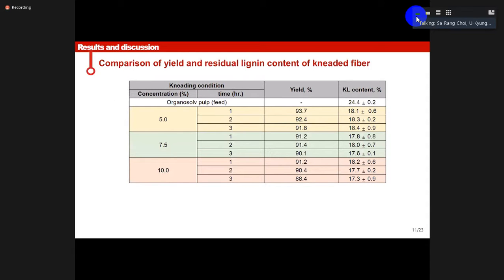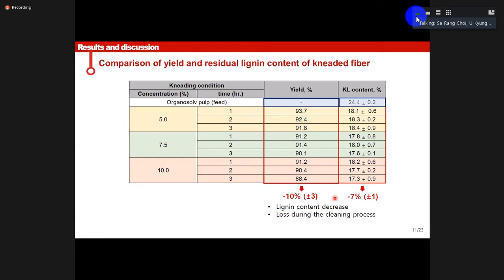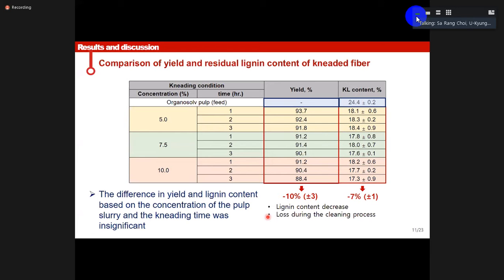The results and discussion. These slides show the yield and lignin content of kneaded pulp according to the pulp concentration and kneading time. After the kneading process, the pulp yield was reduced by up to 10%, and lignin content decreased about 7% due to the alkali treatment. The decrease of lignin content affected the yield decrease, and the washing process also caused a loss that affected the yield decrease. However, the difference of yield and lignin content along kneading conditions was insignificant.